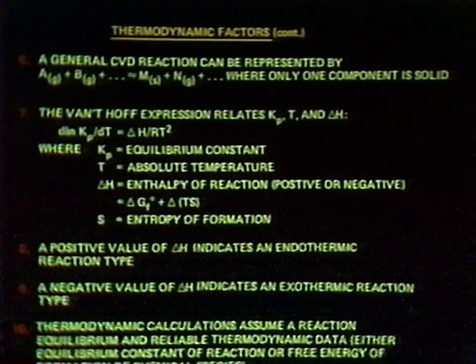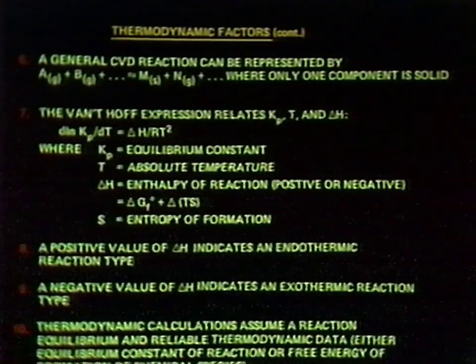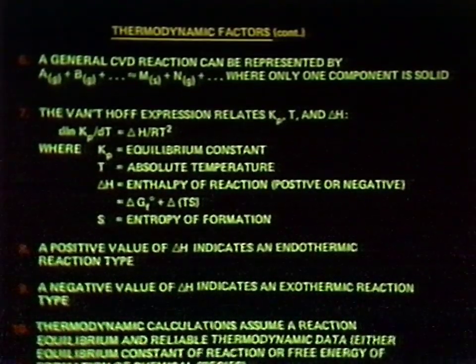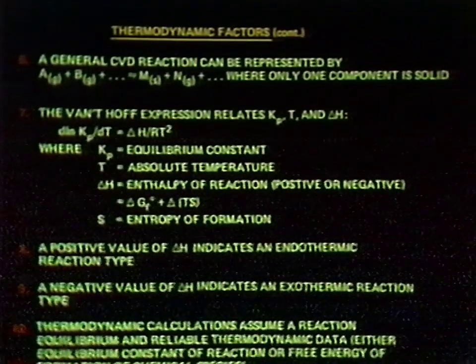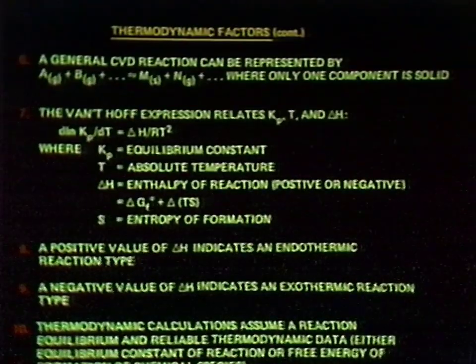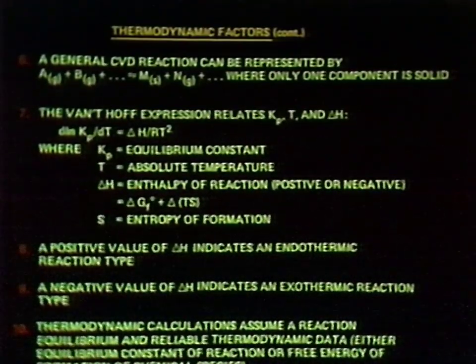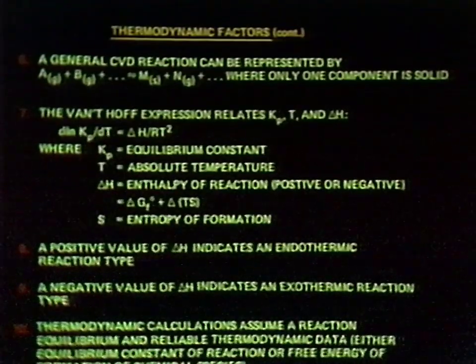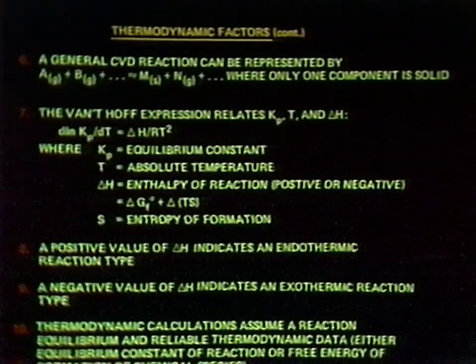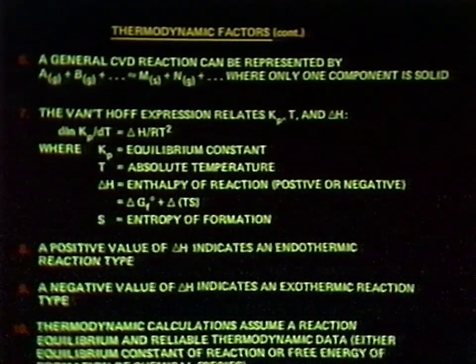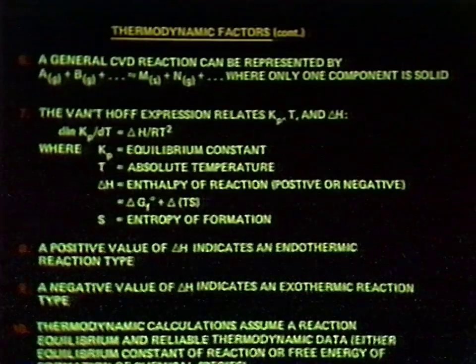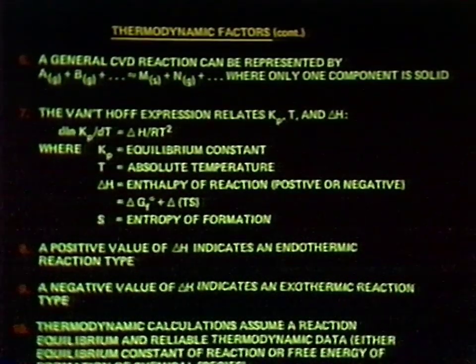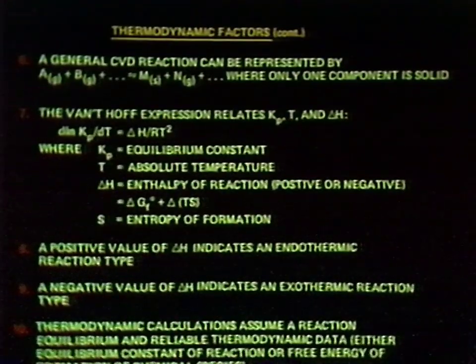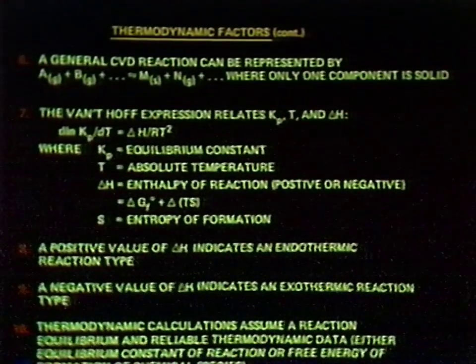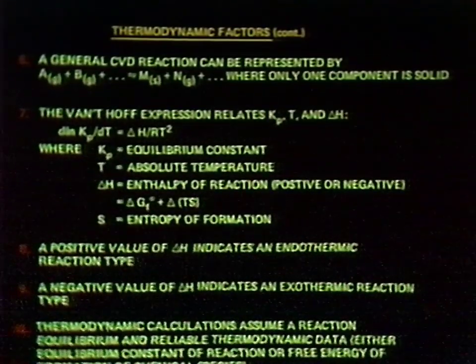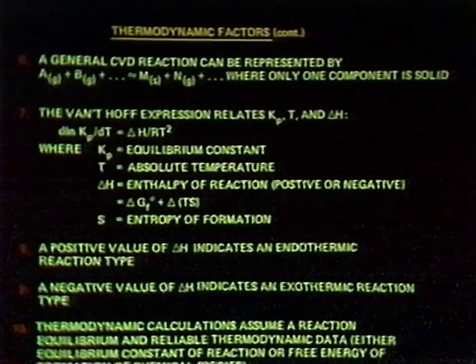If that is the case, we can now calculate by means of the Van 't Hoff expression, which relates the K sub P, the T, that is the absolute temperature, and the delta H by the equation shown. And the delta H, incidentally, is the enthalpy of reaction, which can be positive or negative, and which can be calculated from the delta G sub F plus the T times delta S, S being the entropy of formation. And of course, as we all remember, positive values of delta H indicate an endothermic reaction type, whereas a negative value would be classified as an exothermic reaction type.